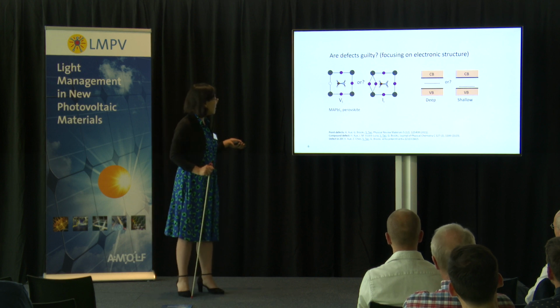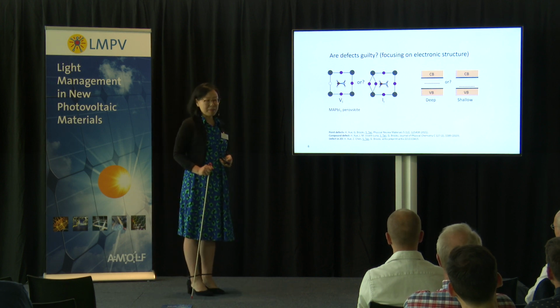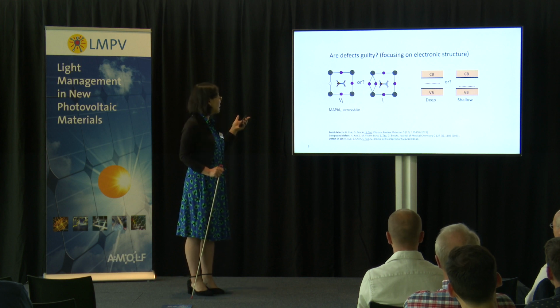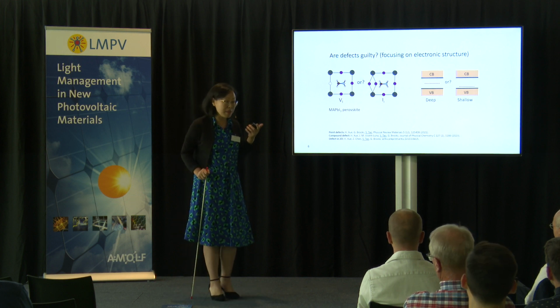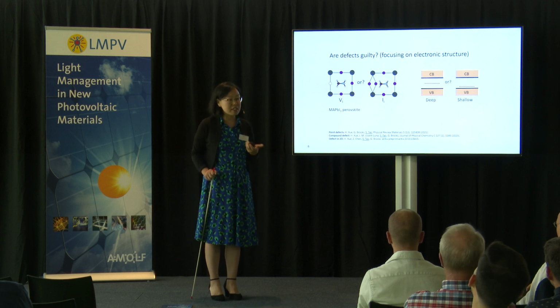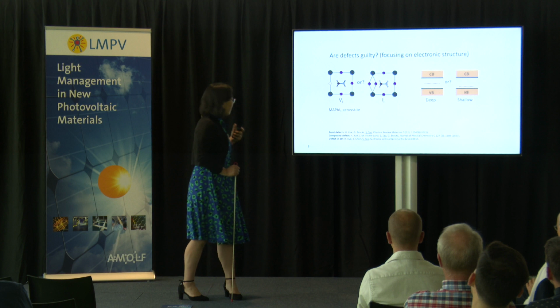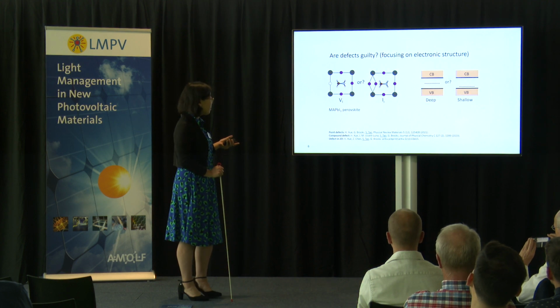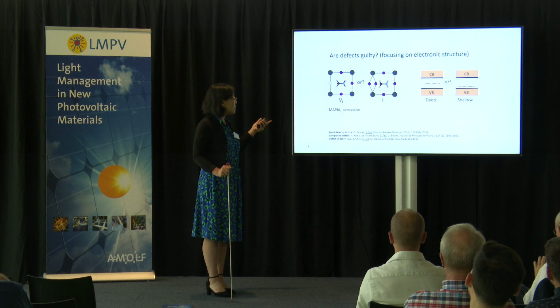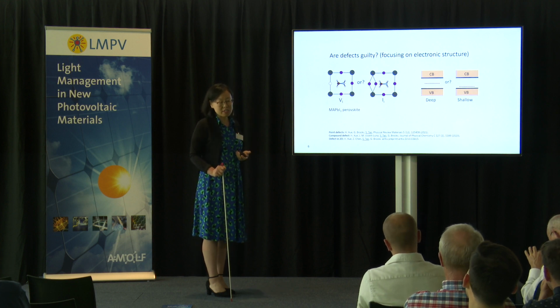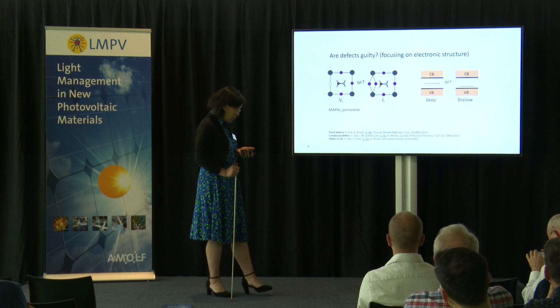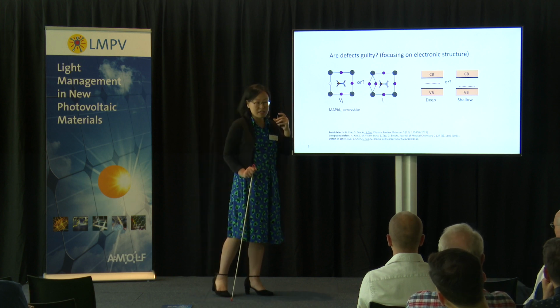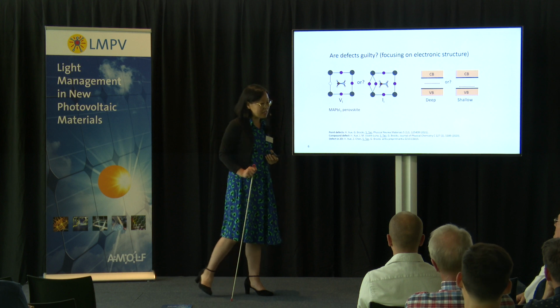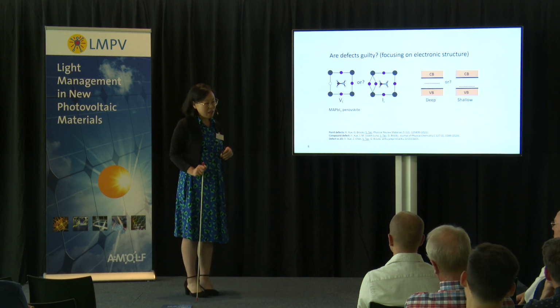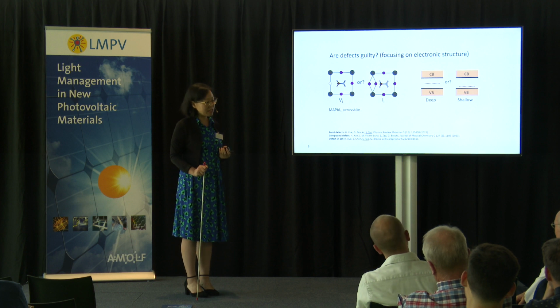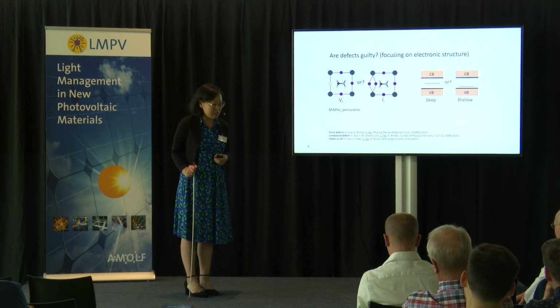So typically we know that in this type of material there can be a lot of defects. Typically they are characterized with either a missing atom or an extra atom, called vacancy or interstitial. And so this uses MAPI as an example. And we're looking at how thermodynamically easy or difficult it is for such a species to form. If we get knowledge of that, we can also look at how this defect level lands on the electronic structures. If in the band edge, they're not harmful, they can be thermalized easily. If in the middle, they cause loss of efficiency.